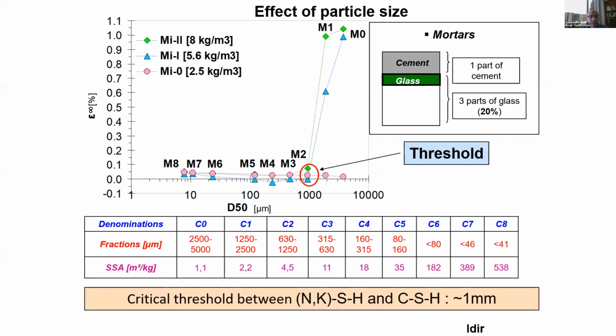But if your material is too coarse, the threshold here is around 1 millimeter, but mainly we use 600 and 800 micron. And you can see that higher than that, you have a threshold and a huge expansion because it's reactive. And you go, at this threshold, from CSH to alkali rich gel.